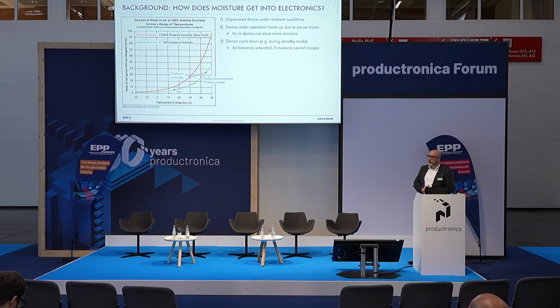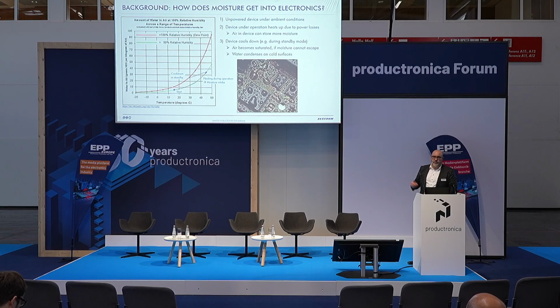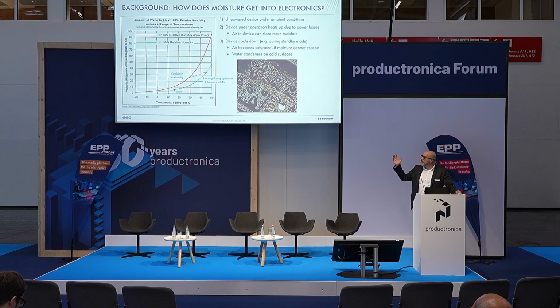And then it can happen that humidity builds up on the PCBA, as you see here. This might not always happen in one cycle; it can also happen over multiple cycles, so a pumping effect can occur. So why is this kind of temperature change and humidity buildup an issue in mission-critical electronics?